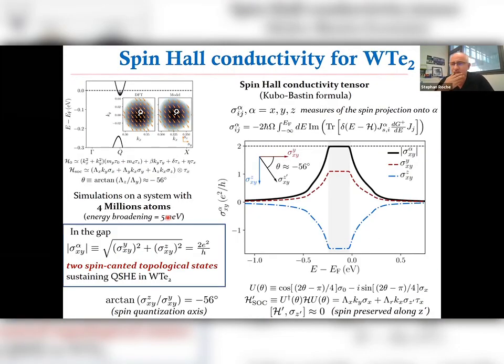So we did this type of calculation here. It's a lot of equations, and there is the reference to the paper, which was published in Physical Review Letters. But basically, we could confirm that indeed the onset of the quantum spin Hall effect, the possibility to visualize boundary states which are topologically protected, is related to the specific band structure and the lowering of the symmetry of these materials.